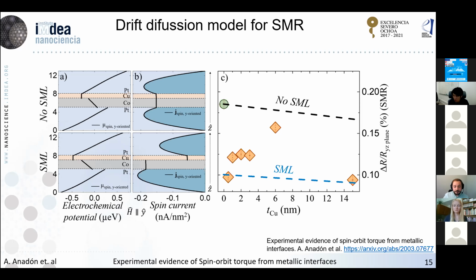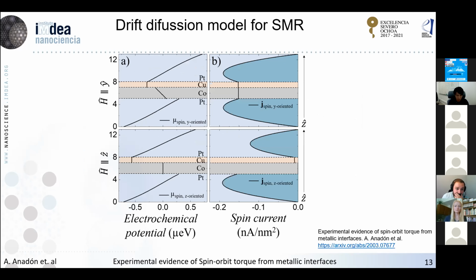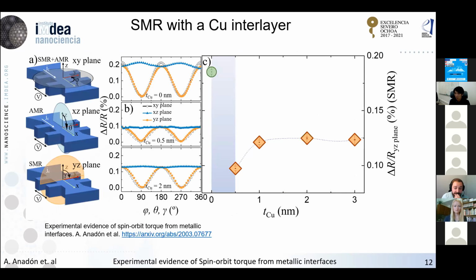accumulation. Okay, so I have a question here from Saul. Can you distinguish between copper enhancing the spin orbit torques and the copper layer blocking the SOT contribution from the top copper platinum interface? Yeah, this is basically what we try to do by analyzing the spin Hall magneto resistance.